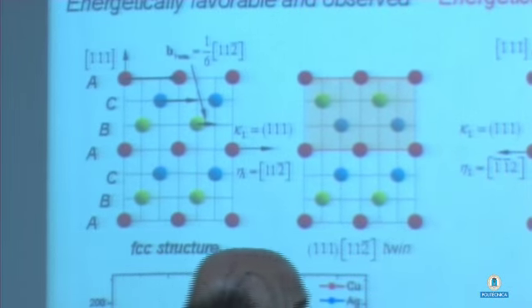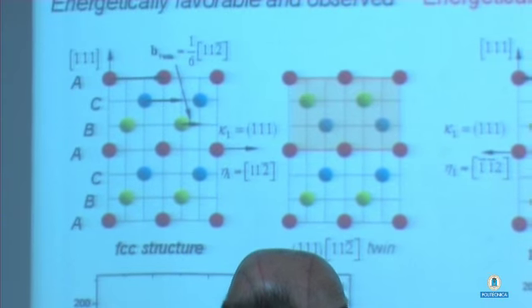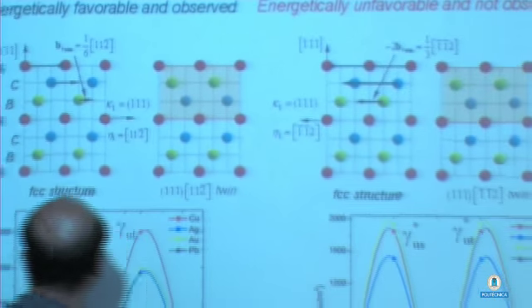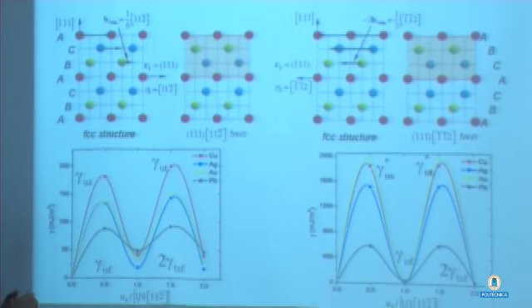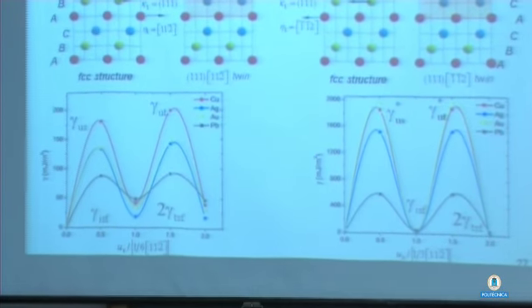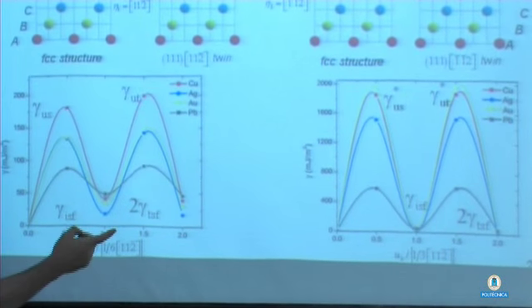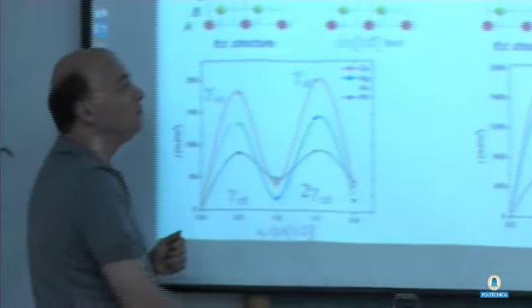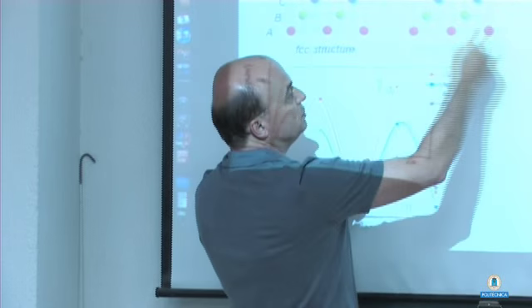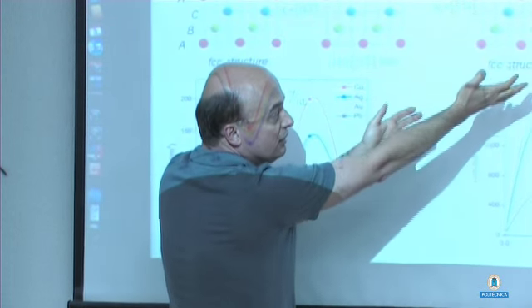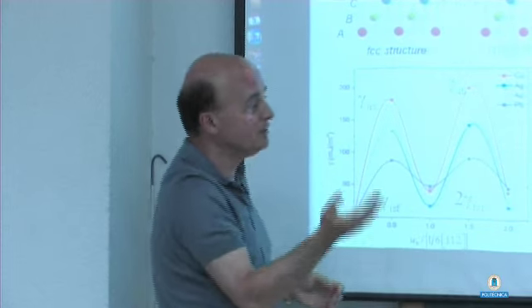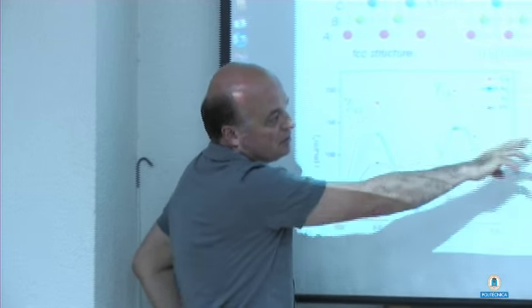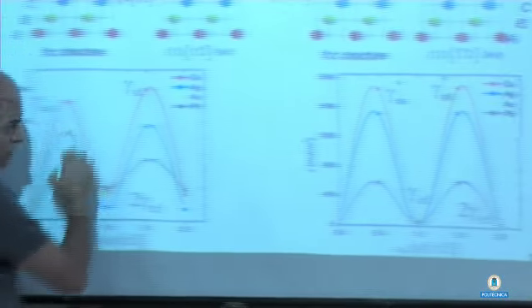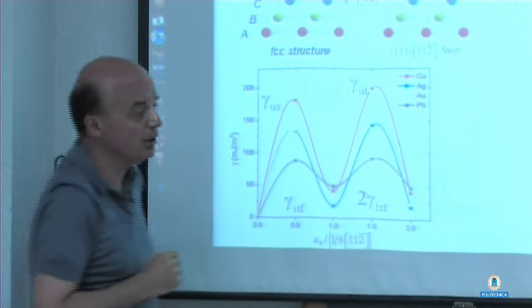And the gamma ISF is the same between here and here. But look at the peak. In this case, you are going through a gamma USF of the order of 2000. Here you're going through a gamma USF of 200. So clearly, if you had a model just based on ISF, you would say that you could get twinning here because ISF here and ISF here are the same. What's different is the unstable gamma UTs. For that matter, gamma USFs are different as well.